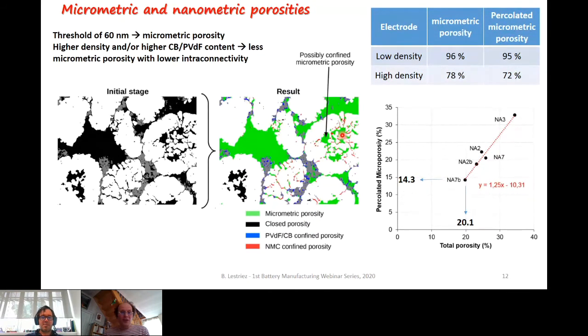But this porosity can only be accessed through, you can see here these red pores that are the nanochannels observed at the crack grain boundaries inside these NMC clusters. And finally, you have these blue pores that is the nanoporosity inside the CB PVDF domains.